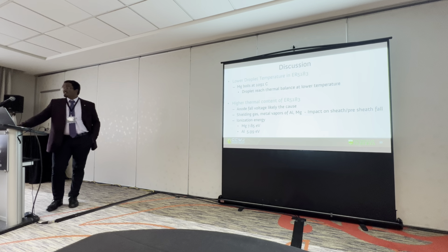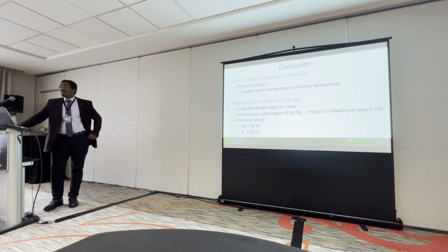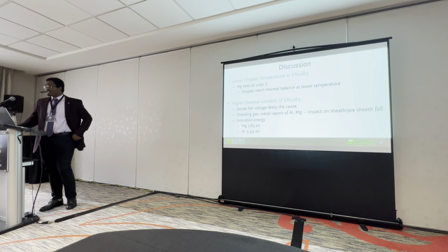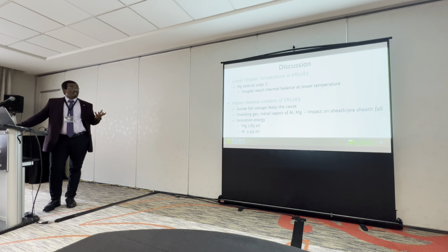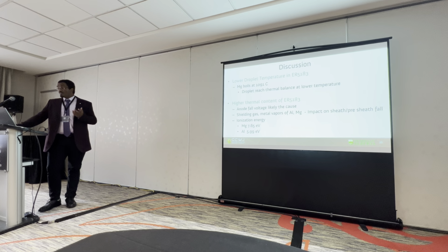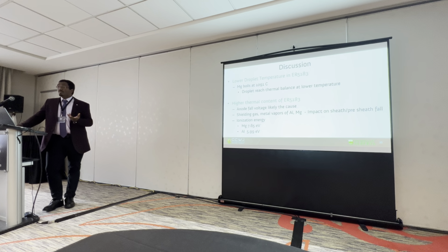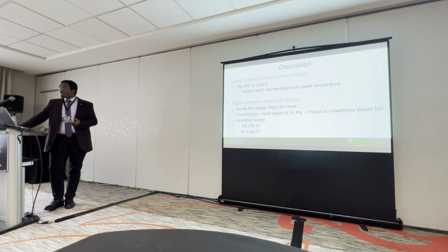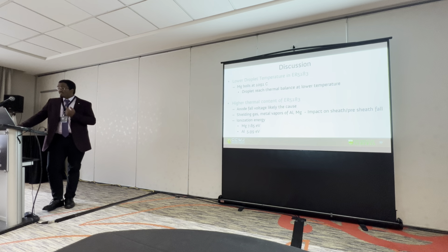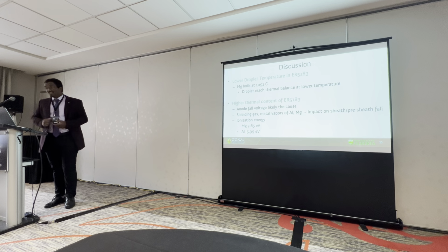So based on the energy balance with Joule heating at the electrode extension, the thermal energy from the contact tip and the contact resistance, we could say that the cause behind the higher thermal content would be mostly due to the anode fall voltage. But how it actually affects it is because of the shielding gases which we use and the metal vapors of magnesium and aluminum. As said in the last presentation, magnesium and aluminum both evaporate to a very high extent at high currents, so we can say that these vapors could impact the sheath or pre-sheath fall. And also magnesium has a higher ionization energy than aluminum, all of which could play an impact, causing it to have a higher thermal content, but that is yet to be researched fully.